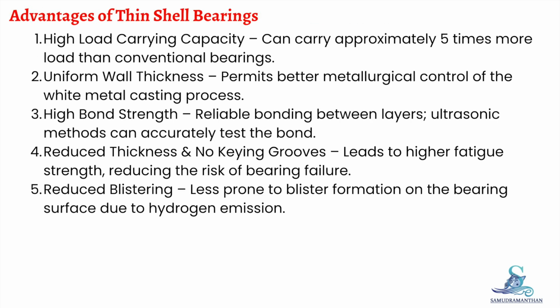What about the advantages of thin shell bearings? Well, they can carry about 5 times the load of conventional bearings. The uniform wall thickness allows for better metallurgical control, and they have high bond strength, which can even be tested accurately with ultrasonic methods. Reduced thickness and the absence of keying grooves lead to higher fatigue strength, and these bearings are less prone to blistering caused by hydrogen emission.